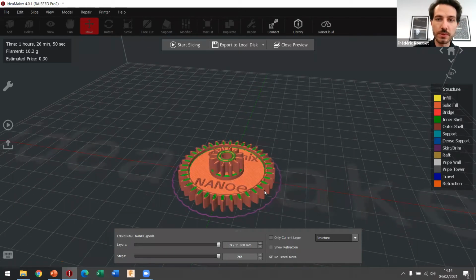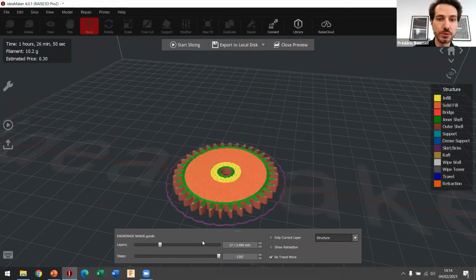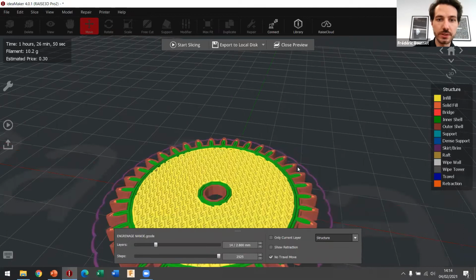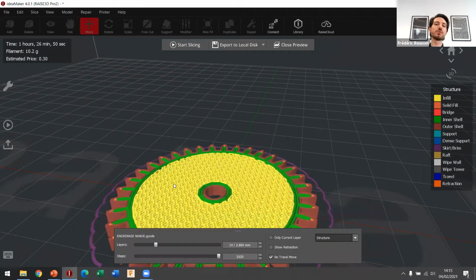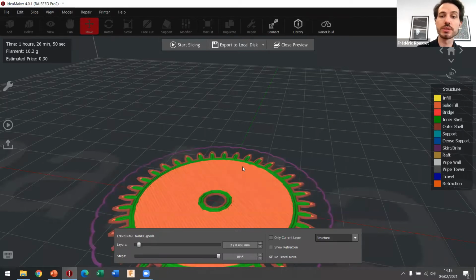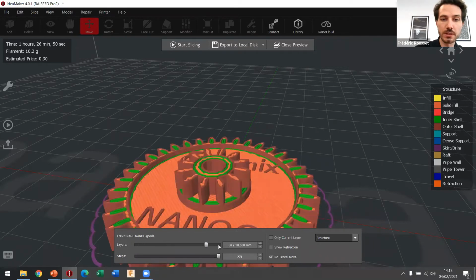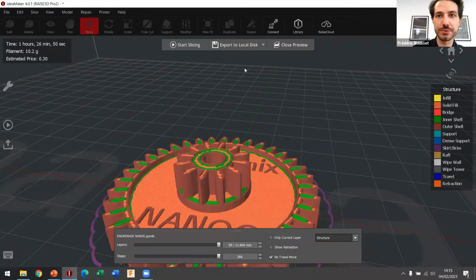This is just the skirt, just to see if the filament is extruding well before starting to print your piece. So 3D printing, you are going to do it layer by layer, of course. In yellow, this is the infill. So you have to do an infill that should be around 100%. You can have different patterns of infill, of course. You have different layers. So the shells, you have 1 outer shell and 1 or 2 inner shells. I'm going to dive into this more after I explain the different parameters. And you have 5 bottom solid layers so that your part is well closed, as well as 5 top layers. You cannot see them, but they are 5 top layers.